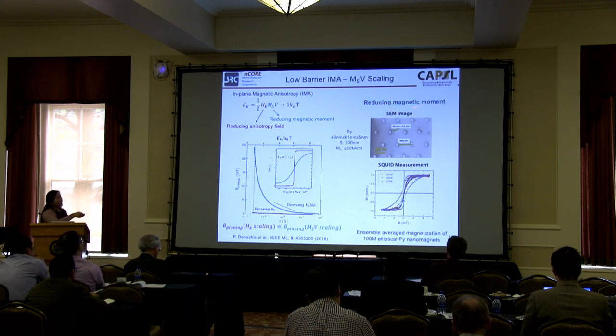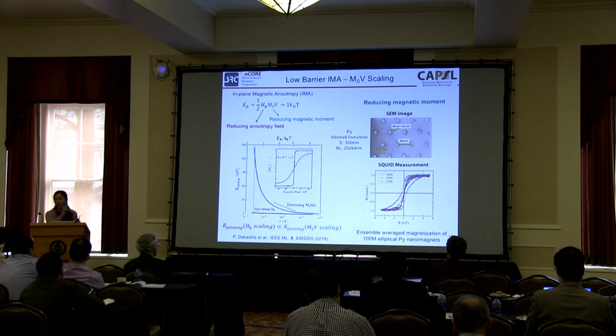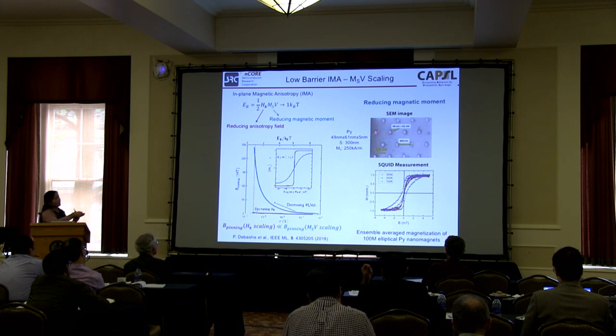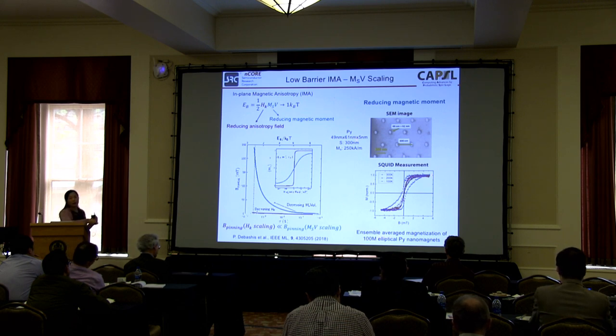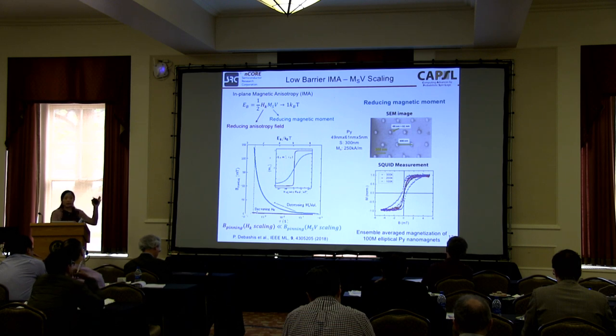And we also worked with the MsV reduction. Here, we keep the oval shape. Normally, the industry's memory bits are oval shaped because we want easy access. We keep the oval shape, but the volume has been decreased by patterning the size to be very small. Then again, we fabricate 100 million of these magnets and take the SQUID measurement at three different temperatures. You see for 300 Kelvin and 200 Kelvin, the black and the red curves, again, we got the desired sigmoid curves that show that all these magnets have low energy barriers. Although they have an easy axis along the long axis, the magnetization is jumping between up and down for most of them at any given moment. And that's why the average, again, shows a sigmoid curve.